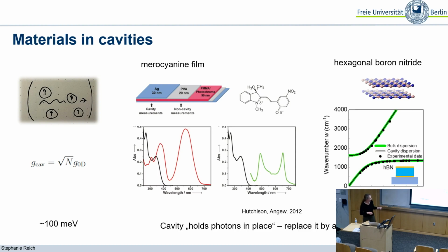And here's another example. This is now not for optical excitations, but for vibrational modes. So this is hexagonal boron nitride and a cavity that's solidly filled with hexagonal boron nitride. And again, the splitting is shown a bit differently here, but you can see that there is a separation between these two branches. This here is the lower polariton branch, and this here is the upper polariton branch. And there is a way to select the wave vector in these types of experiments.